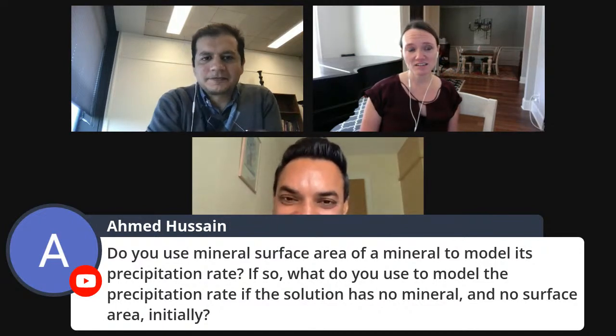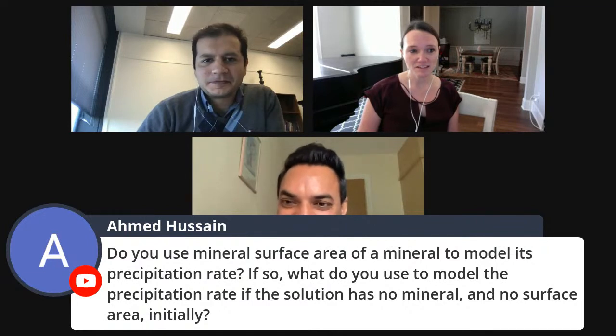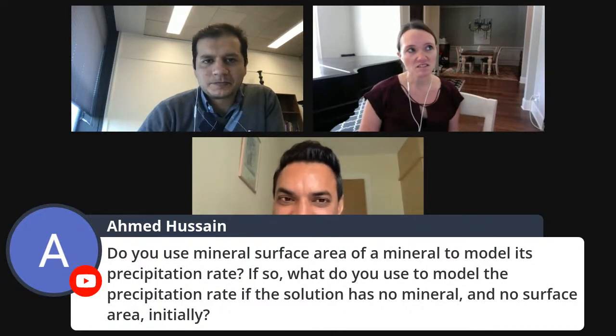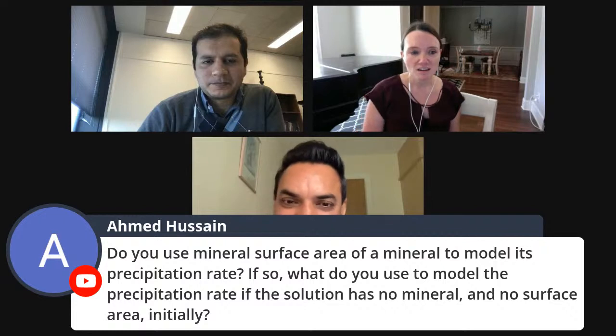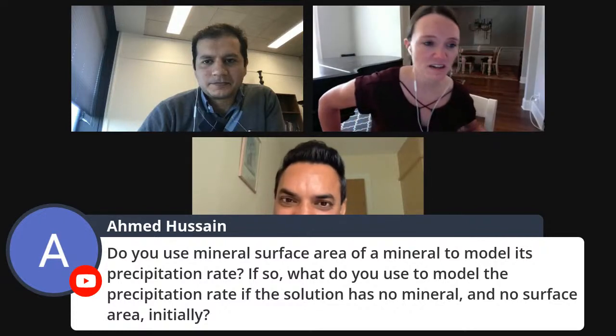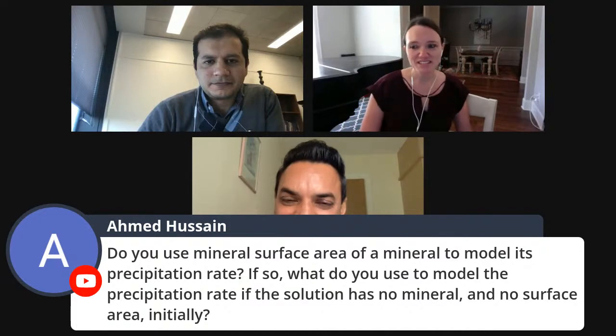And so everything that I've talked about today, at least when we were modeling specific reactions and the accessible surface areas, that really only applies to dissolution. And precipitation is a whole other challenge that I don't really have anything specific to share with you yet about, but it is definitely another challenge, because you also have to account for nucleation, right? And there's the activation energy barrier you have to overcome. And so whatever we've done so far has not focused so much on simulating precipitation, which is very challenging, but in improving the simulations of dissolution.